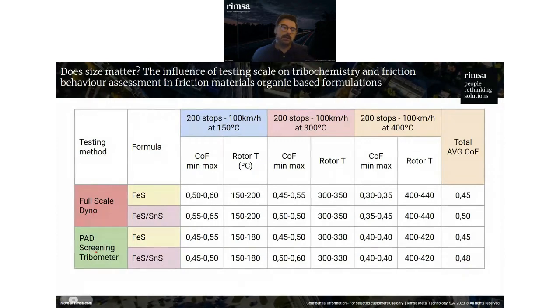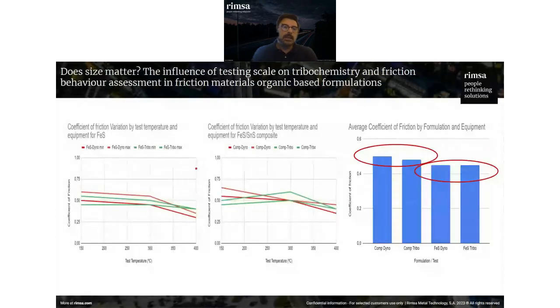You will see here in a more visual way, this is the evolution of the coefficient of friction in dyno and in tribometer in green. And here is the average of the coefficient. This is for each temperature, the evolution, and this is the average. So we can see to some extent that when we compare the different sulfides, we are getting the same trend whether it's in dyno or in tribometer.